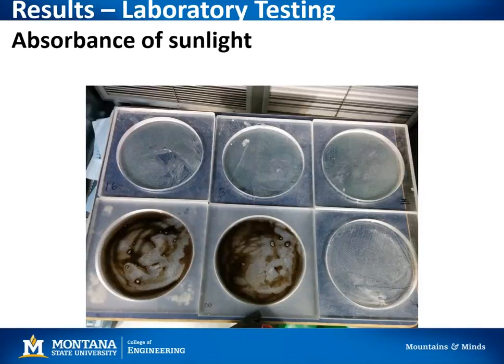Another aspect of the lab testing that we looked into was the influence of UV light. So we looked at the absorbance of sunlight, not only if it impacts the product in terms of degrading it, but also does it influence the product if it's darker? Does it melt more product? Here you can see this is the ice melting test again in the cold chamber. And you can see there's an ice lens with some product put on top of it. And then we expose these samples to what you would typically see in the wintertime in a northern snowy climate. So we're thinking like Idaho, Montana type of sun exposure.